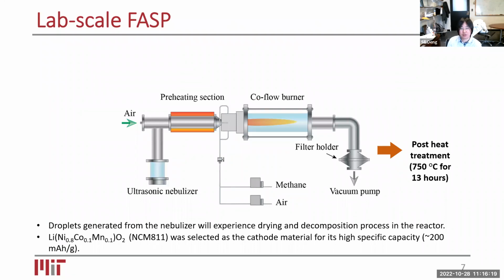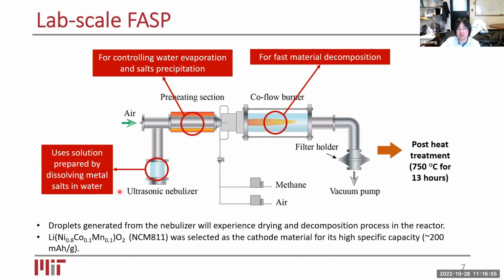So this slide will give you a brief introduction about the experimental system that we built in our lab. We call it a flame-assisted spray pyrolysis, meaning that there are actually two heating elements. So the precursors, I hope you could see the laser pointer here. Different from the co-precipitation method, we have solutions with all the important active materials in the lithium-ion battery cathode materials. So including lithium, we also have the other transition metal oxide salts, all dissolved in solutions. And via this ultrasonic nebulizer, we can introduce droplets into these two heating sections.